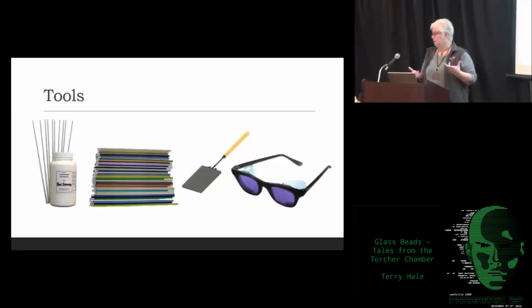The basic tools that I use, and I have some of this up here, the mandrels. People say, how do you get the hole in the glass? I kind of start with a hole, which is the mandrel, and put the glass around it. These are stainless steel 316L uncoated welding rods. Stainless steel, like I said. They're dipped in this clay mixture, which is like a clay slip, just a watery clay mixture that's got graphite in it. The end of it's dipped, and everybody always says, why do you have those sparklers?